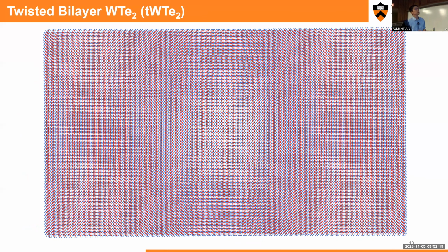But we didn't see any lattice reconstruction in this large twist angle. If you go to much lower angles, there may be a lot of lattice reconstruction. And so let's move forward to the anisotropy measurement, or the electrical transport measurement.